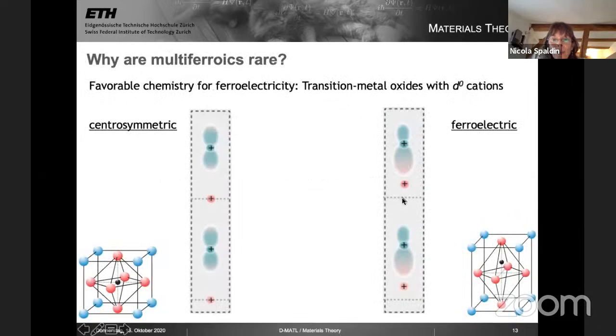And so chemically, this is an energy lowering process, because as this cation moves towards the oxygen, the electrons that are in the oxygen can spill towards the cation, which doesn't have any electrons in its d shell, and make a partial bond formation. This bond formation is energy lowering. So the fact that the titanium 4+ doesn't have any d electrons, it's able to accept electrons from the filled oxygen shell, makes this process of ion off-centering energy lowering. If there was no bond formation, I'd just be trying to push two ions together, and that would increase the energy. So the d0-ness of the transition metal cation is very favorable for off-centering to make electric dipoles.